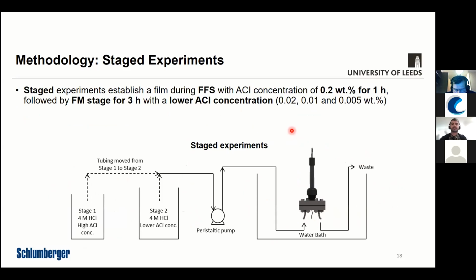For staged experiments, these are slightly more complicated, but essentially using the same equipment, same technique. So for these particular experiments, we had a film forming stage where we had 0.2% of the corrosion inhibitor for 1 hour, which was followed by a film maintenance stage for 3 hours. And that was using a lower inhibitor concentration. And these are the 3 concentrations we used, which were the same as the control experiments.